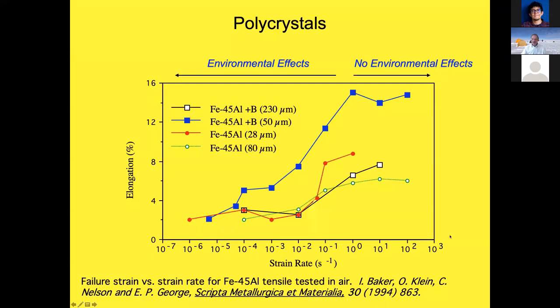In fact, this is work we did quite a long time ago, looking at a similar sort of effect in iron aluminum. These are 4 different alloys of iron 45 aluminum with different grain size and different boron contents. This is the elongation as a function of strain rate. You can see that at slow strain rates, we get very little ductility, and independent of the grain size or whether we have boron or not, we get about 2% elongation. When we strain at high strain rates, we can actually get more ductility, and we can see the effect of these metallurgical parameters. This alloy, which has both boron and a fine grain size, gets more ductility than the other compositions.